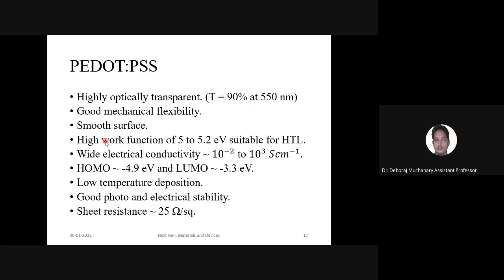Next is the high work function. The work function is around 5 to 5.2 electron volt. This 5 to 5.2 electron volt is suitable for a hole transport layer. They are used in some organic solar cells, and in perovskite solar cells also we see that these materials are useful as a hole transport layer because of this high work function, with a value of around 5. 5 is the work function of gold, and gold is used as an electrode in some perovskite solar cells also. So it is approximately near to gold. It is even more than gold also.